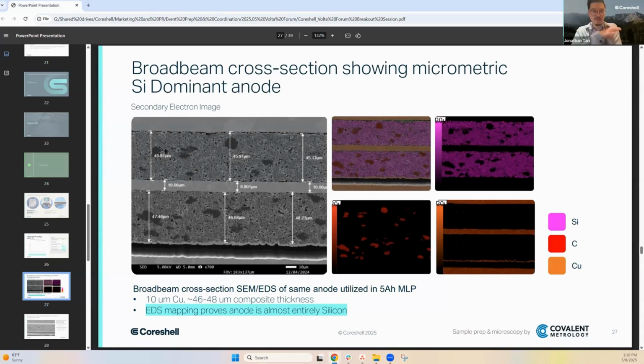We don't know how much of a role that's playing. So again, we believe we can go to 100% silicon of the active material. There is still 5% additives. So I'm kind of the belief that we should be able to get to a graphite-free system because, as people have mentioned, it's not like it's distributed that well in our electrodes. And it doesn't really participate in the electrochemical process. So hopefully that means that it's not that critical of a component for us.